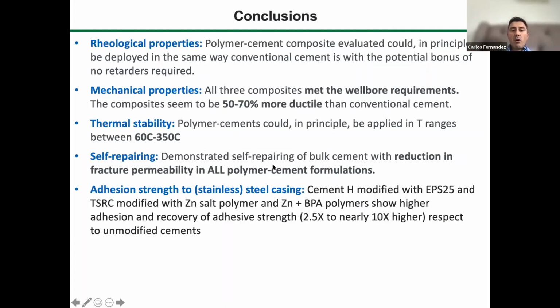Self-repairing: we have seen in all the polymer cement formulations that the permeability ratio before and after the healing event is much lower than the control cements. We also saw in the previous talk that I gave a few months ago that the compressive strength is recovered between 80%, and in some cases it's even higher than 100%, 120%. This is because there is a combined healing event that is not only due to the polymer filling and bonding to the cracks, but also the continuous hydration of the cement that also fills those cracks and sometimes makes the compressive strength even higher than before the damage occurred.